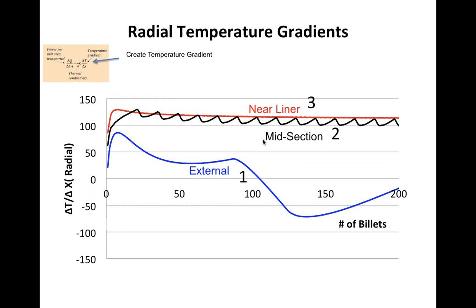We did a simulation on these three different designs, and the graph shows the first factor that controls the temperature extraction or temperature stability in the container: temperature gradients. You can see in number 1, the gradients go from positive to negative about every 100 billets. That means the gradient is changing all the time. Design number 2 has a big fluctuation every 15 billets or so. Design number 3, when you move the heater close to the liner, is very, very stable.